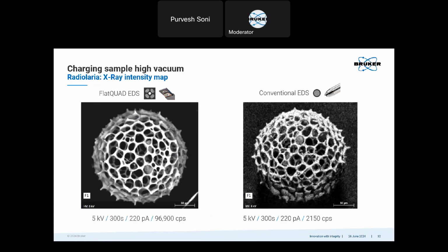And this is to show you how the collection efficiency is improved and the shadowing and topography is minimized with the FlatQuAD. If we use FlatQuAD, we get the full X-ray intensity map, and there is collection from all the sides of the sample. But with a conventional detector, because of the shadowing, we barely get any signal here. And also, you can see the signal to noise ratio is quite good with the FlatQuAD, but quite poor with the conventional. So the background signal is almost equal to the signal from the material. And also you can see the difference in count rate under same probe conditions.